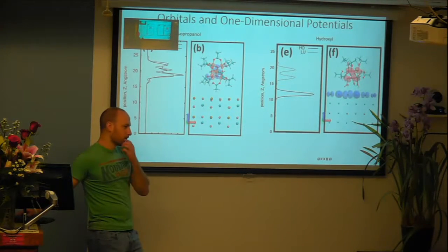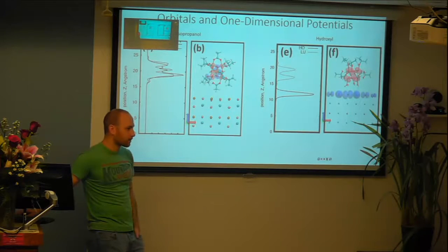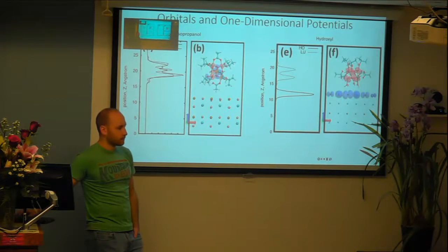the red band. Okay, so in the first case you have both HOMO and LUMO on your nanoparticle, and in the other case you have one localized on the nanoparticle and the other localized on the surface, and this is what you call a charge transfer. Right. But my understanding is that the energy of absorption is very different between these two materials. So you can easily tune the absorption just on the range of your perovskite or on the range of your quantum dot, because energetically they're very different, right? So you can imagine that you're really exciting just one system rather than both of them.